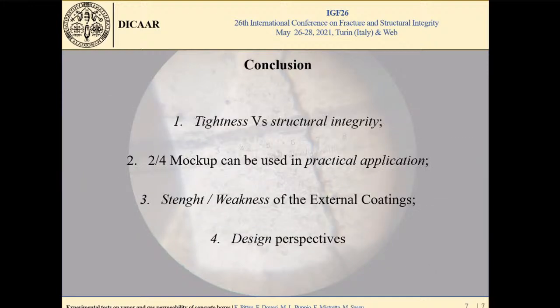So in every case, a separation of the function of mechanical resistance of concrete and the tightness of coating or other elements is suggested in reinforced concrete structure. So the results of this experimental campaign show that mockup A and C can be effective with this purpose. And a point of strength, in my opinion, is the possibility to inspect an external coating with respect to an internal one, and to check by time this performance. Considering the limited thickness of the wall of the box tested, and the poor quality of the concrete, the coating of mockup A and C shows the relative best performance.